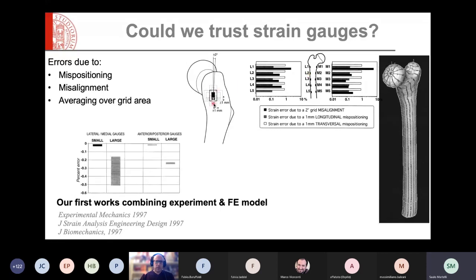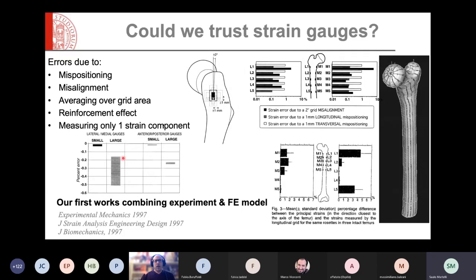We also worried about the effect of measuring the average strain on the grid surface. And again, the strain gradients are not easy to measure experimentally. So we used, again, this simulation to assess the effect of a small and a large strain gauge and how this would underestimate the measured strain.